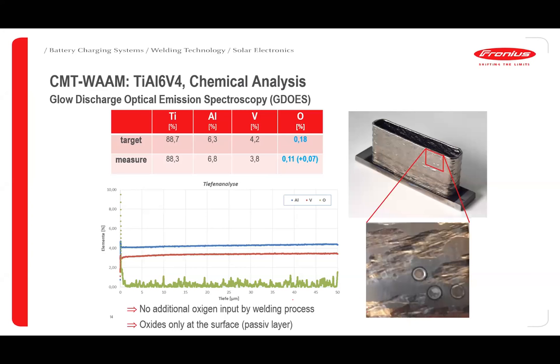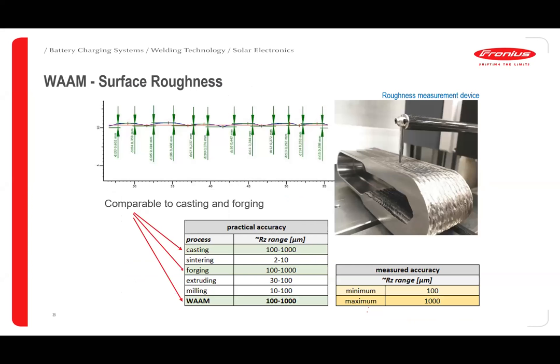Moving on to another important aspect of our study, which is the surface roughness of the component we have produced. It was already matching the casting accuracies, the Rz average values of 100 to 1000 micrometers of casting and forging, and we were able to meet these two metrologies of processes, and the WAAM was also giving close to around 100 to 1000 micrometers.